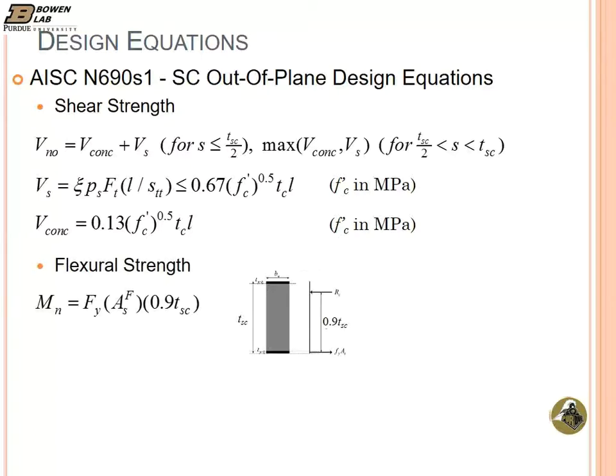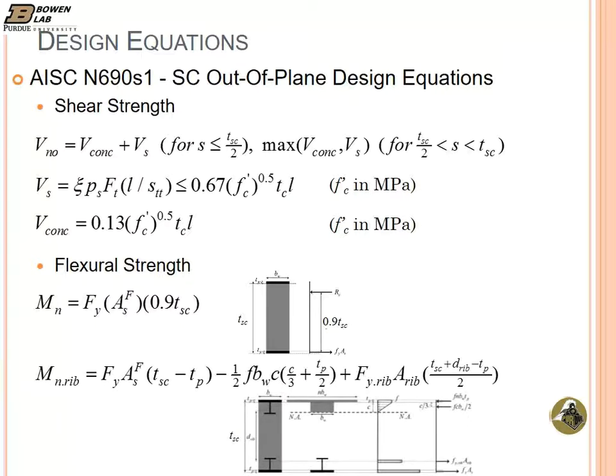And then for flexural strength, it's the simple equation that we developed. It's assuming a force couple occurring about 90% of the section thickness away from each other. For sections that also have steel faceplate stiffeners, so for MWS type 2, we had the inner plate in the longitudinal direction, right? So in flexure, the inner plate also contributes to bending. To account for that flexural contribution of the inner plates, or what we call the faceplate stiffeners, there is a longer equation provided in the appendix to give better estimates of the strength.